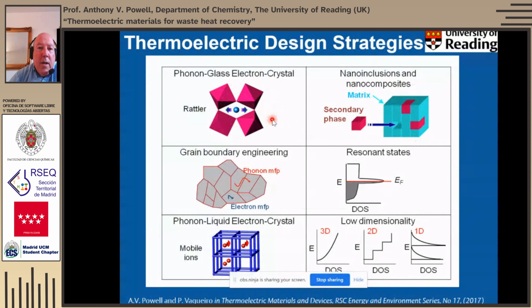So for instance, the phonon glass electron crystal has been quite a popular way of achieving high performance, because what it does is introduce cations into cavities which are really too large for that cation, and as a result that cation shows localized vibrational modes. It's termed a rattler. They're often referred to as rattling modes, and those rattling modes can interfere with the phonon propagation, so it's affecting that kappa L component of the thermal conductivity without necessarily impeding the electrical transport, which happens through some kind of framework. This is a skutterudite, which we'll be seeing later.